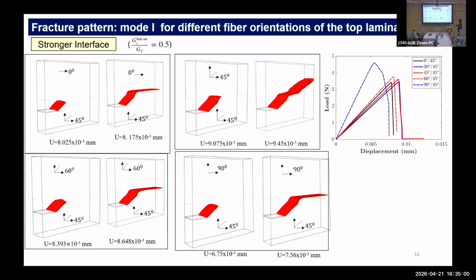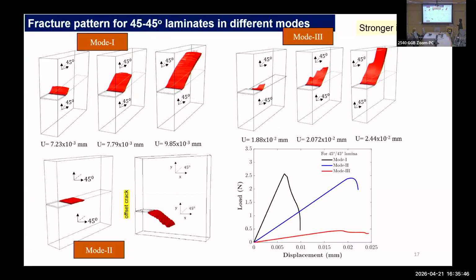However, if the interface is stronger, again, I showed you some results in the 2D case. We have done the same experiments in 3D, okay? And we have seen similar results: up until about 45 degree, it starts from the notch tip, follows the bottom fiber orientation, goes to the interface, remains there for a while, and then follows the top fiber orientation. But in 60 degree and 90 degree, it goes to the interface, then interfacial delamination is favored. And of course, the resulting phenomena that we are seeing is a competition between the individual toughness of the lamina and the toughness of the interface.